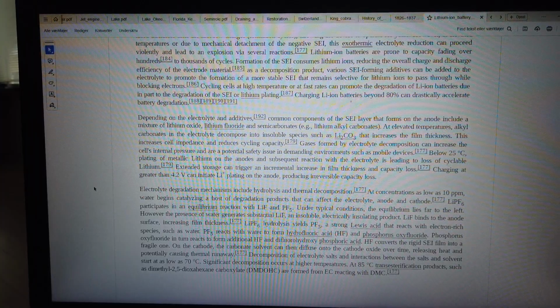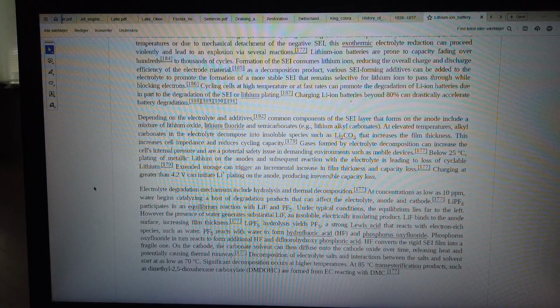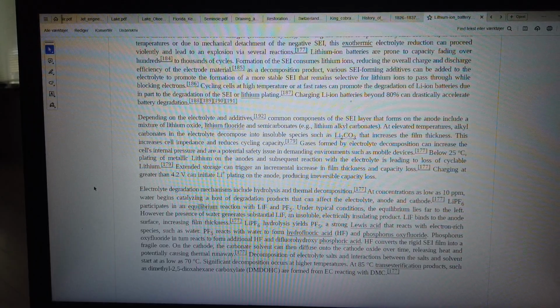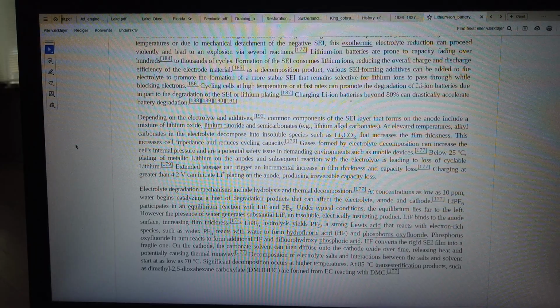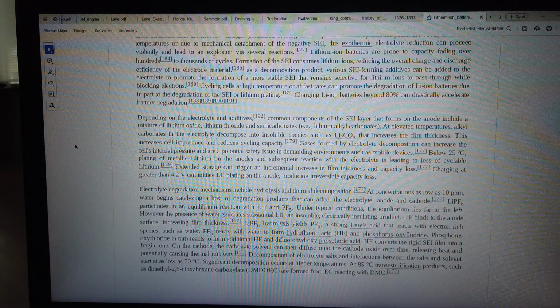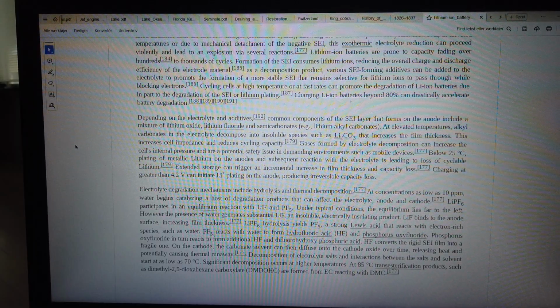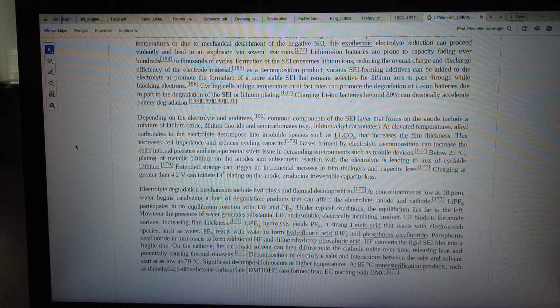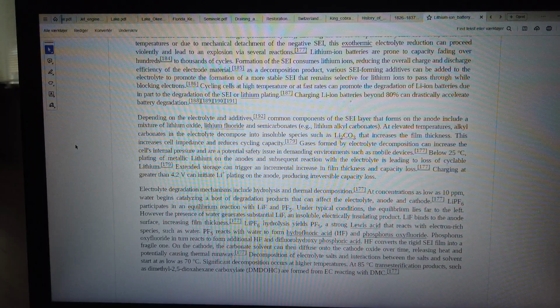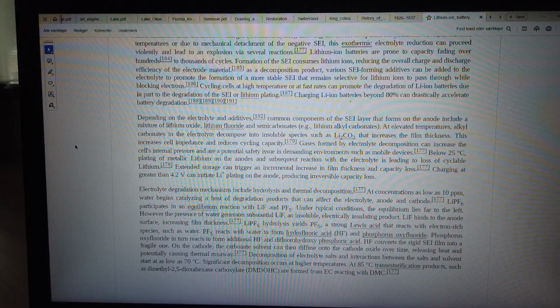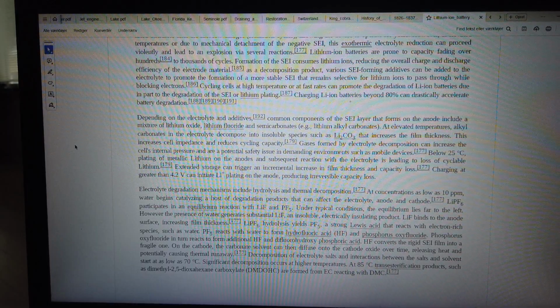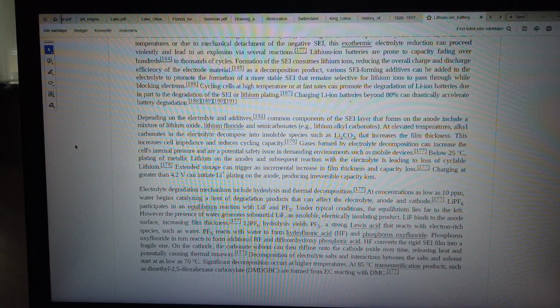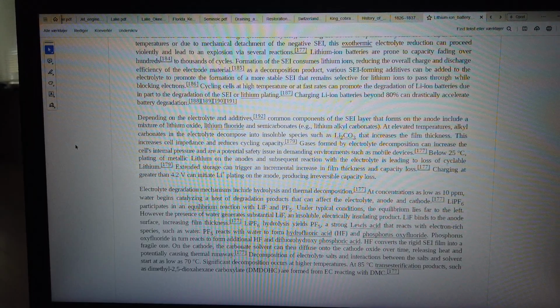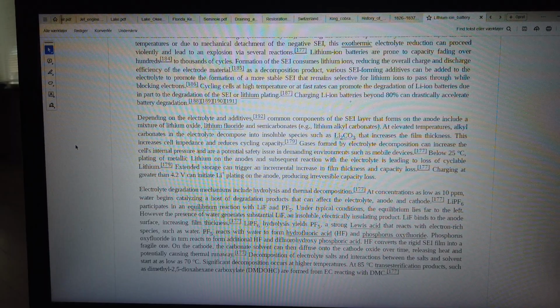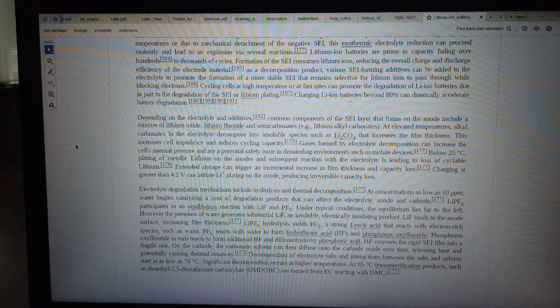Electrolyte degradation mechanisms include hydrolysis and thermal decomposition. At concentrations as low as 10 ppm, water begins catalyzing a host of degradation products that can affect the electrolyte, anode and cathode. LiPF6 participates in an equilibrium reaction with LiF and PF5. Under typical conditions, the equilibrium lies far to the left. However, the presence of water generates substantial LiF, an insoluble, electrically insulating product. LiF binds to the anode surface, increasing film thickness.